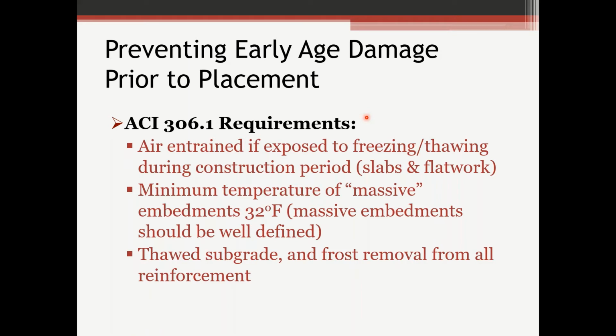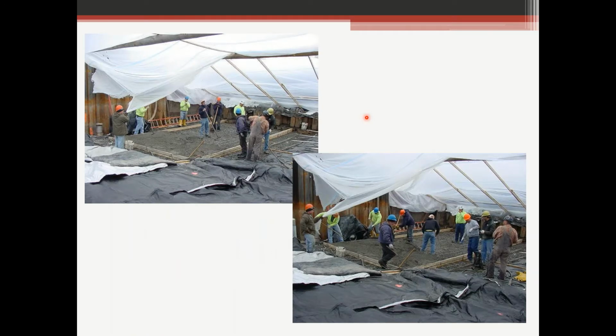Minimum temperature of massive embedments needs to be 32 degrees. Massive embedments really isn't defined very well in 306.1. Large anchor bolts, things like that, just those large steel embedments that are going to retain a lot of cold. Obviously concrete's not going to bond to frozen rebar very well, if at all. Subgrade's got to be thawed out, and frost has got to be removed from all reinforcement. So those are the requirements in 306.1. There's obviously more requirements, but those are some of the big ones. This is that project in Ticonderoga.